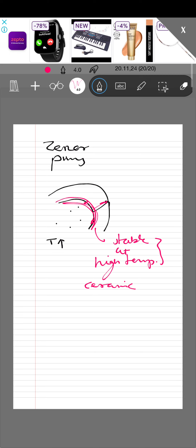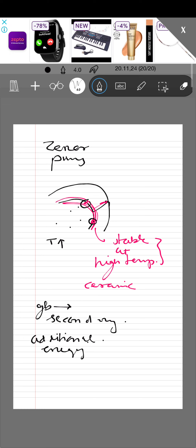Since the driving force required for grain boundary growth also depends upon the several secondary phases which might have developed at the grain boundary, the secondary phases, like in this case this additional high temperature stable phase, if present in the grain boundary, require additional energy for the grain boundary migration. And since additional energy is required, this leads to inhibition of grain boundary motion.